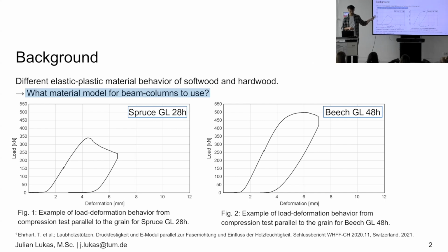But just to show you where the difference is, when we have, for example, a normal compression in the direction of the grain, the normal test we know from the EN 408, we have for spruce a load deformation curve. We have around 85% of the maximum strength, we reach our elastic range, and then we have a plastic strain, but it's not really that long. This kind of load deformation behavior is already included in the well-known formula we know from the Eurocode.